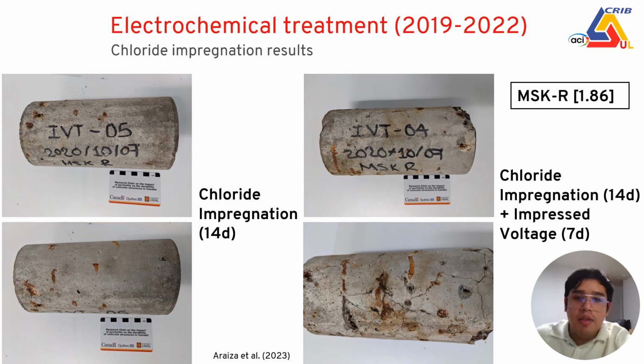Finally, after having the setup complete and controlling all the parameters, and trying with a non-reactive aggregate to see our chloride impregnation, we go to the next step, which is testing our reactive material. As you can see here in the picture, these are concrete specimens using the sulfate-bearing aggregate material from the quarry of Tuparribia. This aggregate, we select some from stockpiles, some aggregate with a high quantity of material.